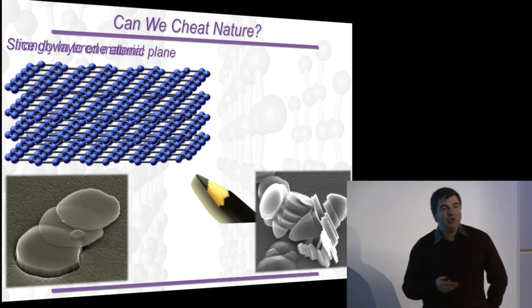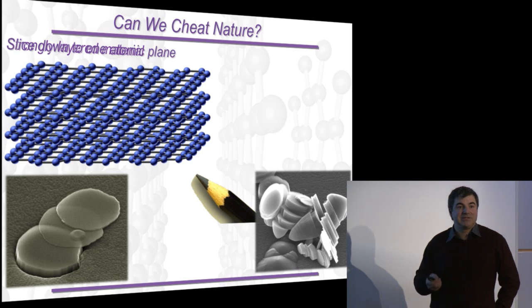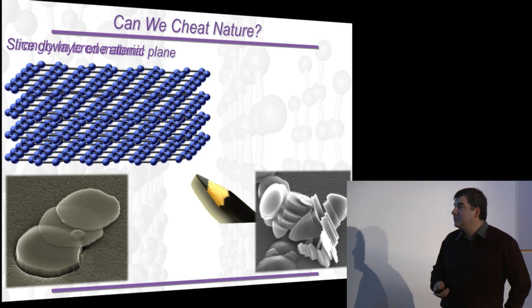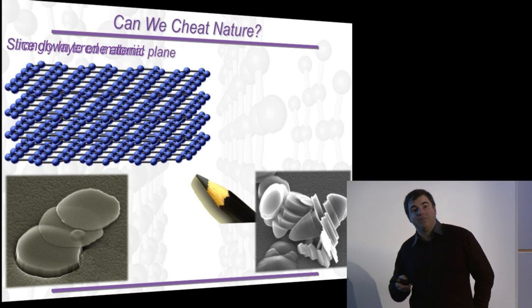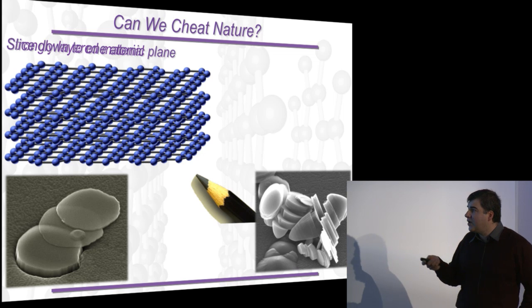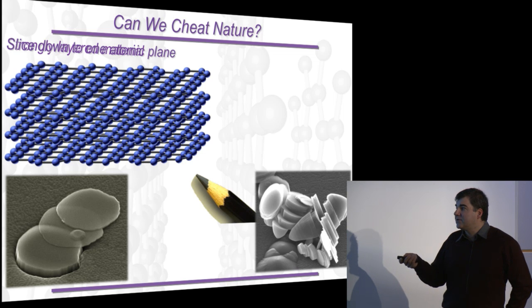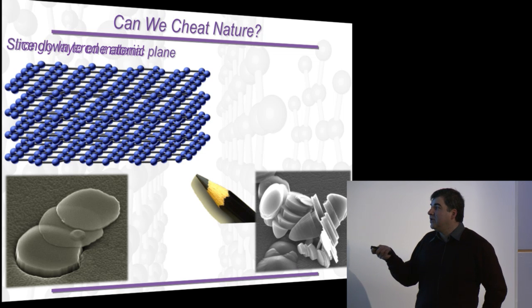However, what you need is quite thick particles, because you want to see what you're writing, though there are quite a few which are quite thin, which you don't see, and that's exactly what is of interest for us, because the idea is, can we try to isolate and slice it down to the monolayer? Quite a few people tried it, and so here is a pencil trace on a special substrate under a microscope. The purple color is the substrate. It's silicon oxide, and the graphitic particles of different thicknesses can be seen as different colors.